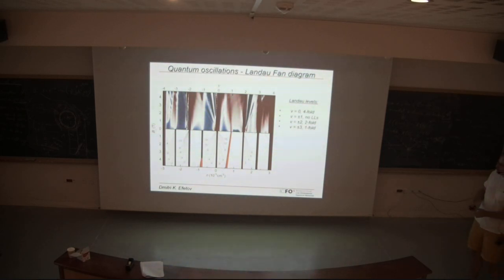Actually, I removed that data line. So we actually see the Hofstadter butterfly here. The Landau levels start to cross, etc. And we are also preparing a manuscript. We made devices with much smaller twist angle, close to the second magic angle, where all of these bands are much closer spaced. We are in a regime where we can access 8 bands. So we have a really complicated Hofstadter butterfly with 8 bands. But surprisingly, only very few states of them survive at high field. I can also discuss with you afterwards, but this is definitely underway.